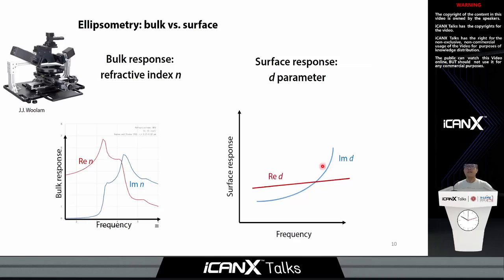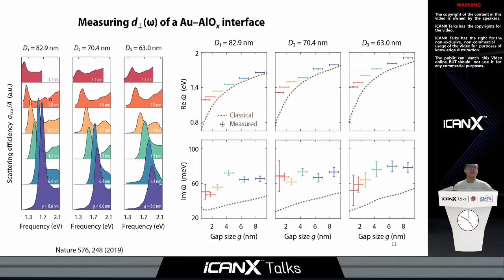So this characterizes the surface response of two materials that comprise an interface. So here's what we do. We do a two-dimensional sweep measurement. We vary the gap size, which is indicated by color, and we also change the diameter of the nanodisk, which is shown by columns. And we track the real part and the imaginary part of the complex resonant frequency, as shown on the right.